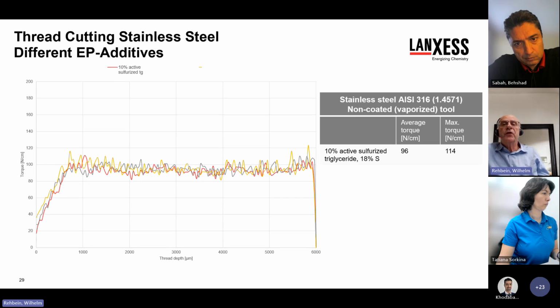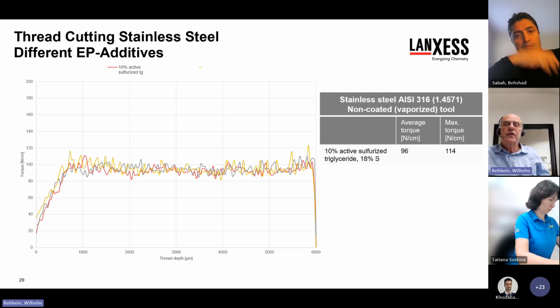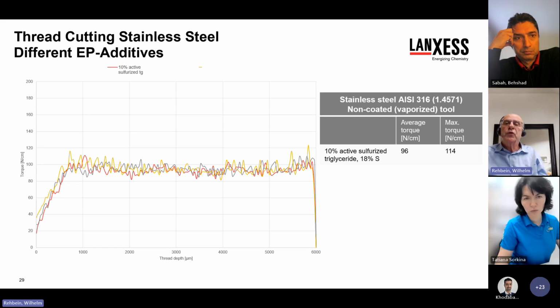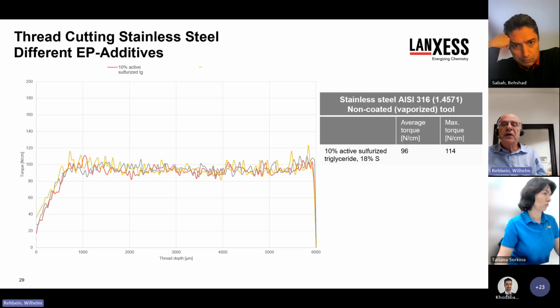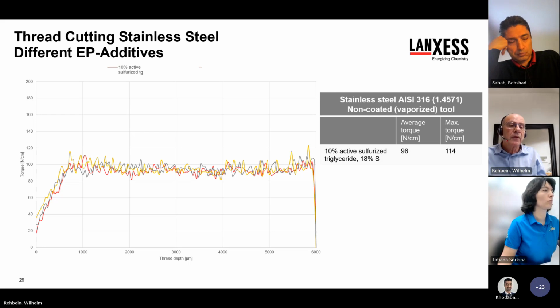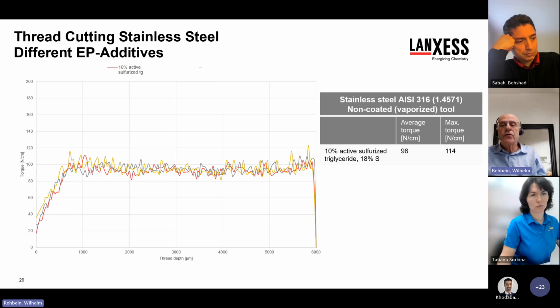Because the highly active sulfurized triglyceride showed the lowest torque, we additionally tested a sulfurized ester with almost similar sulfur content but lower kinematic viscosity. As you can see, in this test with stainless steel, there was no significant difference. But we also tested a formulation containing 10% of a medium chain chlorinated paraffin, which contained 50% of chlorine. When we compare the torque of the chlorinated paraffin containing formulation with the sulfur-based EP additives, we see that the average torque is quite similar. But the torque curves of the sulfur carriers are smoother and with fewer peaks in the records than for the chlorinated paraffin.